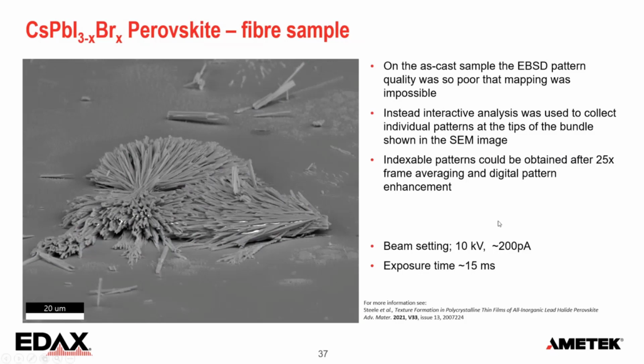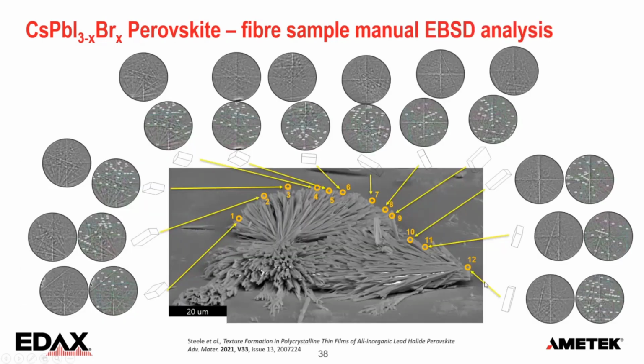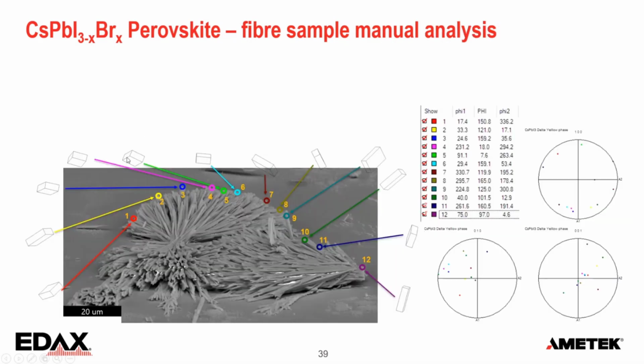Now, here's another one. This is the fiber sample before sintering. If you want to see a little bit more, you have the reference where this material came from, where it's described down here. And mapping is just not possible on a material like this. So what you can do is go in spot mode in the EBSD software and try to hit the very tips of these fibers. If you're lucky, and on most fibers actually that could work, you will get a surface that is projecting towards the EBSD detector. And in this case, I could get those diffraction patterns. I just tried to follow the outside of this whole cluster, of this bundle of fibers. I could get indexing results everywhere. And with that, I get the orientations.